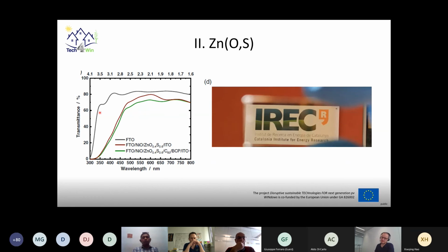You already see some transmittance results compared to the FTO layer. And you can clearly see indeed that the C60 layer, for the complete devices, is reducing the transmittance a bit in the visible parts, as expected due to the band gap. Still, UV filtering is quite good. Visible transmittance is quite good as well, as hoped for, which you can also see for the cell with the C60. You see the cell here on top of an IREC logo, and you can see it's very nicely transparent in the visible part of the light.